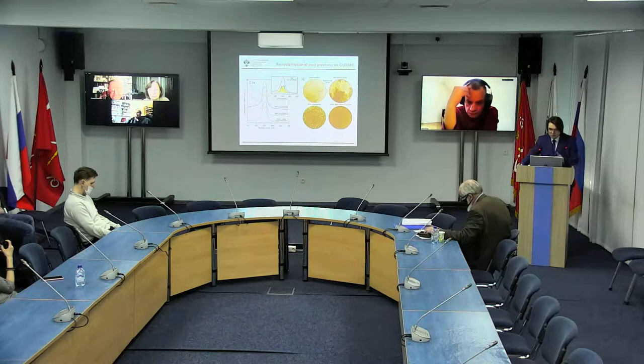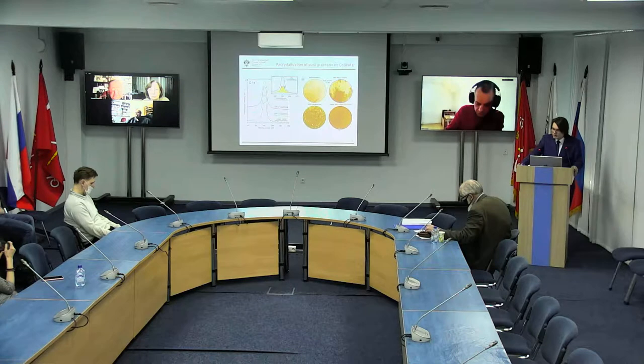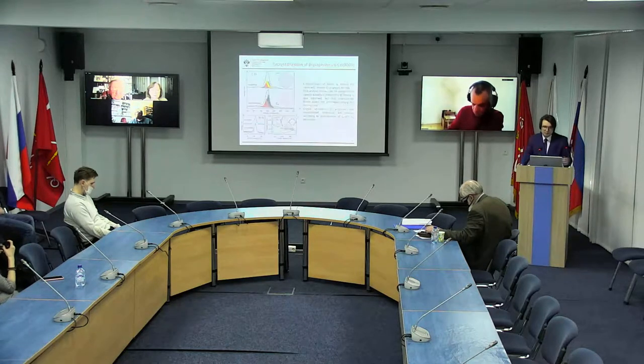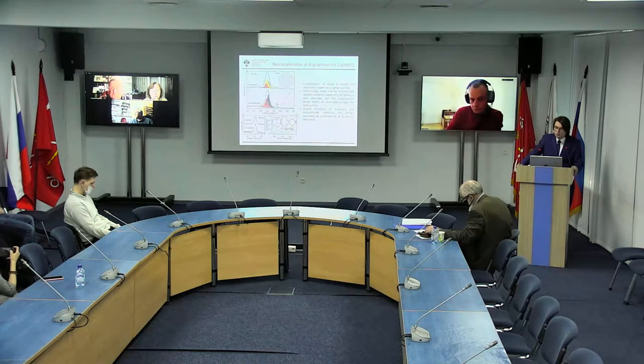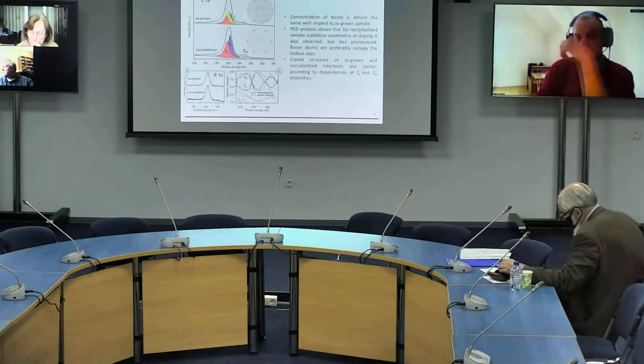As in the case with intercalation with oxygen, we used photoemission electron microscopy in order to visualize the process of recrystallization, and we see the difference quite well between the recrystallized sample and the grown single crystalline sample. We see that in the recrystallized sample we have a lot of light areas associated with polycrystalline areas of non-recrystallized graphene.